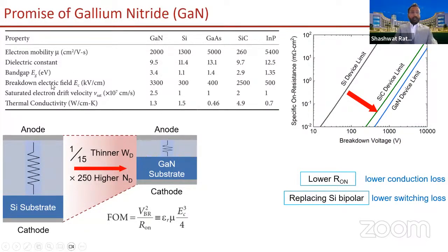Now, what the band gap translates to typically is a critical electric field or breakdown electric field. So this gives you an idea of how much field a unit thickness of a semiconductor can sustain. So let's say that you have about 1 micron of a semiconductor. So 1 micrometer is 10 to the minus 6 meters. If you have that sort of material, and if you're trying to drop electric field across it, this property tells you how much field can you apply before the semiconductor breaks down. So you see that because of a wider band gap, gallium nitride has about an order of magnitude higher critical electric field.